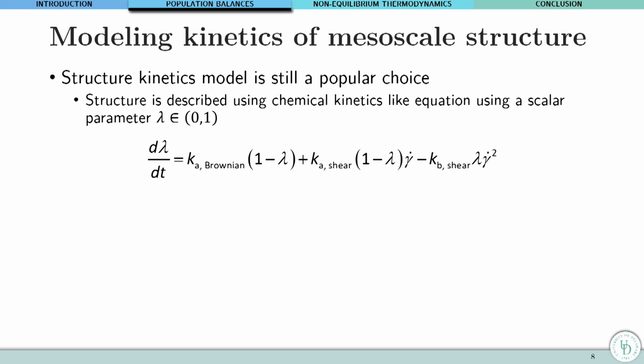Offering first what has been done in the last 20 years in the field, which is basically mostly phenomenological at the microscopic level, trying to describe the changing microstructure through a relaxation equation for a characteristic structural parameter called lambda, typically, which ranges between 0 and 1, 0 describing the completely destroyed structured state, and 1 the fully structured one, having terms which return lambda to its structured form, involving Brownian and shear flow and shear rate contributions, where the primary shear contribution comes in breaking down that structure to reduce it all the way down to 0.